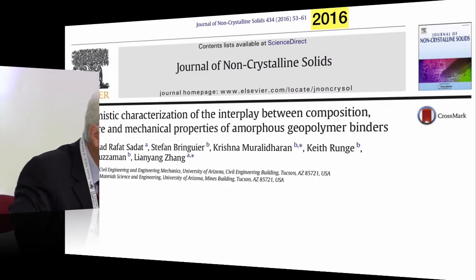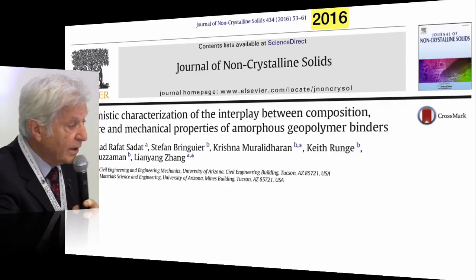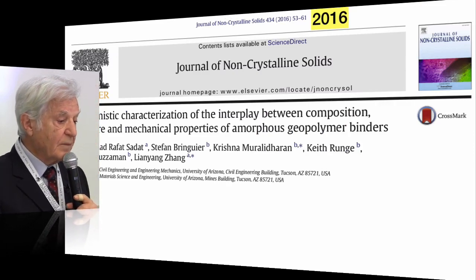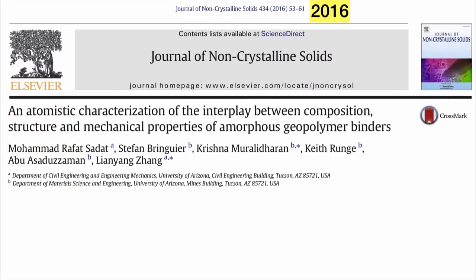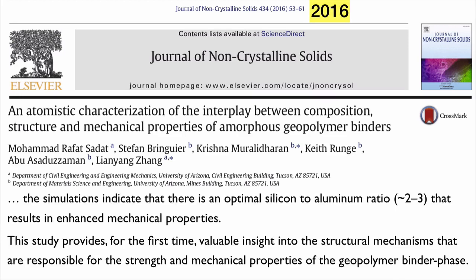And then we find now new papers, for example, an atomistic characterization of the interplay between composition, structure, mechanical properties, and amorphous geopolymer binder. This was done on the computer. The simulation indicates that there is an optimum silicon to aluminum ratio, 2 or 3. This is what we have discovered.